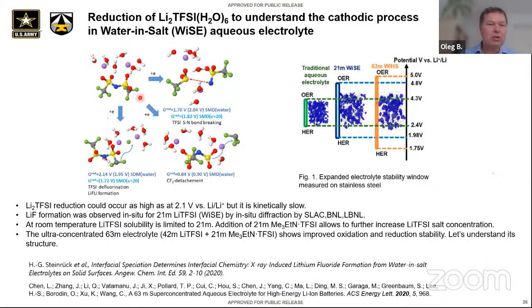Specifically, we can take a simple system. It's a slightly larger system than what I originally included in a paper on water-in-salt. So this system has 2 lithiums bound to the TFSI anion, which is representative for 66% of the anions at 21 molar lithium TFSI in water. And we can look at the reduction reaction when an S-N bond breaks or fluorine gets transferred and gets solvated between lithiums. So all these complexes are in a polarized continuum using SMD, either water or a lowered dielectric constant, as it might be the case for high concentration next to the interfaces when the dielectric constant is lower due to limited ability to relax, right?